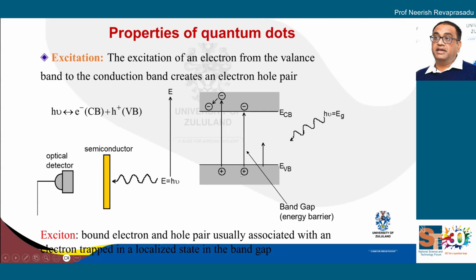And then above 0 Kelvin, you provide energy, and you can excite the electron from the valence band to the conduction band. And when you do that, you have what is known as a positive hole that's left behind in the valence band, and you have the electron now sitting in the conduction band. Of course, these now form what is known as an exciton, a bound electron-hole pair, and it is associated with an electron trapped in a localized state in the band gap. Now, the amount of energy that's required to excite the electron from the valence band to the conduction band gives you the band gap energy.